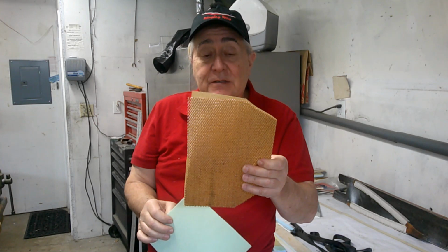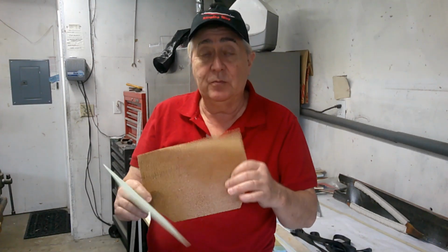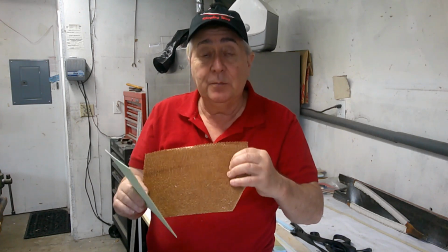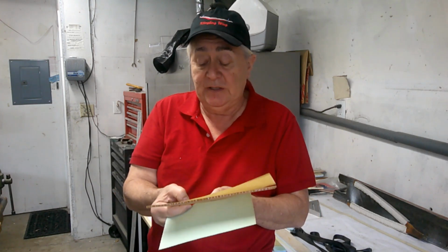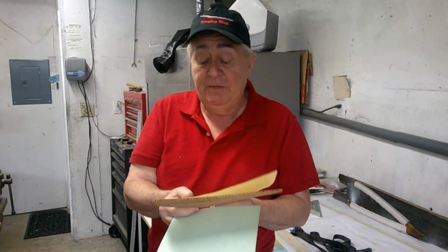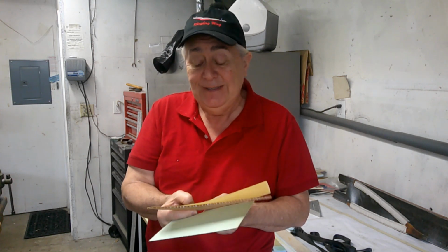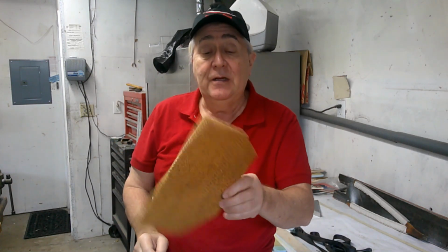Drawback to the foam is it doesn't have but a fraction of the compressive strength that the Hexcel honeycomb core has. And it's very easy to dent it. You can dent it with your fingernail, bump into a rock, it's dented. It doesn't really happen with this honeycomb core. Honeycomb core, because of its incredible compressive strength, is highly resistant to being dented. In fact, if you go so far as to actually force the denting, you're popping the bond loose from the honeycomb core. Anyway, so pluses and minuses on the foam core, pluses and minuses on the honeycomb core.